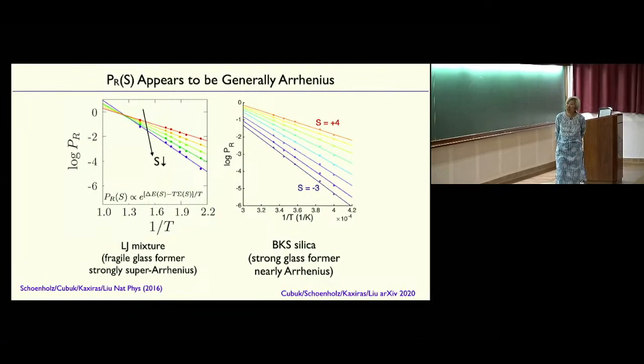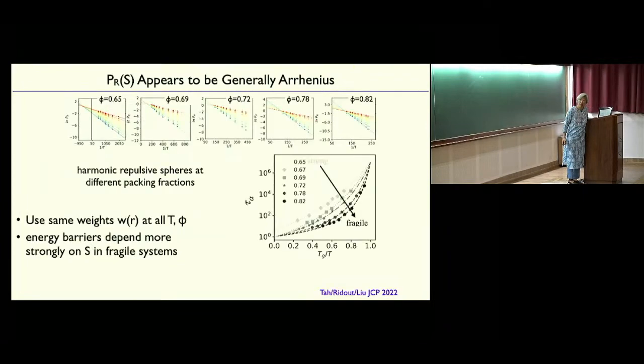I showed you just the results with Lennard-Jones, but here's silica, BKS silica. It's again Arrhenius. So it works on this very strong glass former, which has very different temperature dependence of the relaxation time.